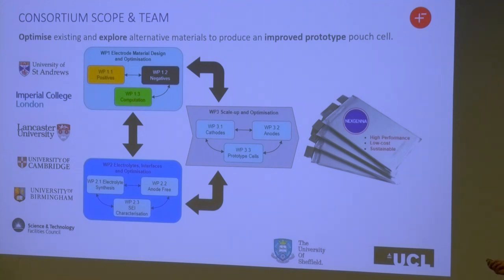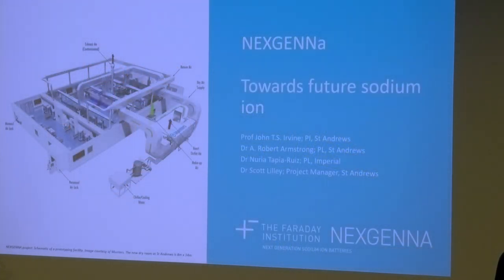So we're looking at all aspects of the battery: the electrode materials, the electrolyte, the interface, which is not my thing, I'm not going to talk about it this evening, but it's very important, particularly the interface between the electrolyte and the negative electrode, because the electrolyte tends to decompose on the surface of the negative electrode. And we're also looking at scaling up to pouch cell size. This is a mock-up of a scale-up facility which has had its official opening last month at Guardbridge near St Andrews and the University's Eden campus.